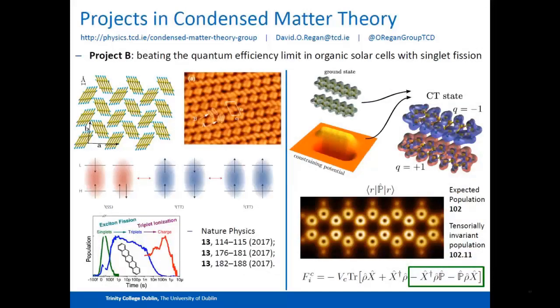Now power generation. There's an effect called singlet fission, which can be used to beat the quantum efficiency limit, the Shockley-Queisser limit on solar cell active layers. The best solar cell that works with just creating electron-hole pairs from photons can get you to 37% efficiency, and you can't go higher. So you need to go to exotic quantum effects, like a single electron-hole pair splitting into two electron-hole pairs with opposite spin.